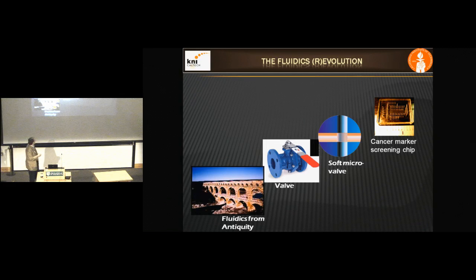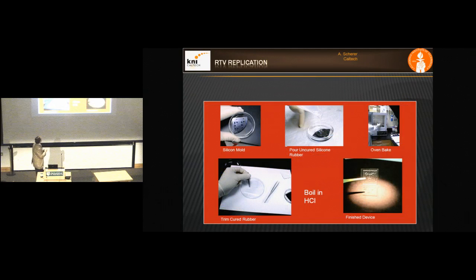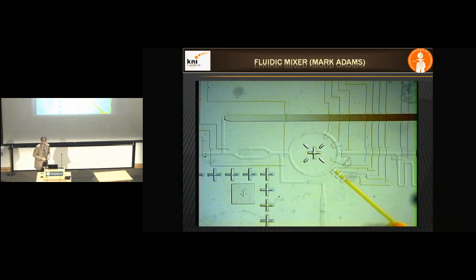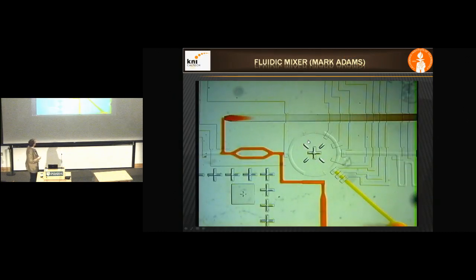In this case, we use a technique that's called replication molding. So we actually print some mold, and then we replicate an elastomer on top of it. Looks something like this. You have the mold here, you pour the elastomer in there, you cure it for a while, and then you peel it off, and you put it on your new substrate. It's essentially a lithographically enabled replication mold. You can build systems like this by using replication molding.